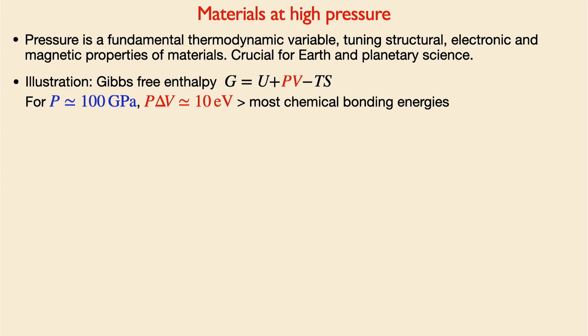And now I add the PV term, the pressure and volume dependence. If I apply a pressure of 1 million atmospheres, which is equivalent to 100 gigapascal, then the volume change in the material, for instance the dependence of the lattice parameter on pressure, times the pressure will be of the order of 10 electron volts. That's more than most chemical binding energies. That means that new chemistry can happen. Very different compounds can form at those pressures, and I will give you an example of that.